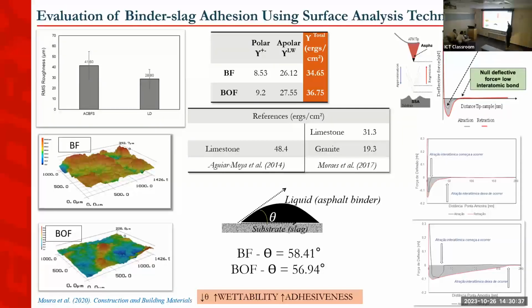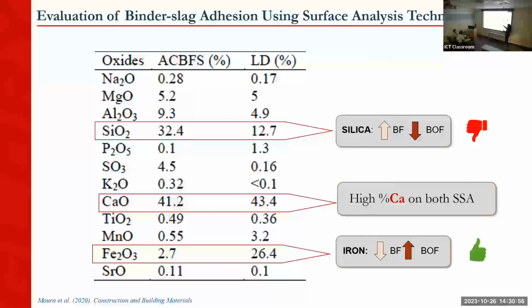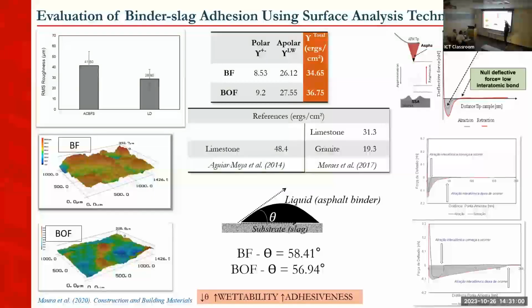Later, we took the AFM tip and dipped it into the asphalt binder. Then we approximated the tip to the slag substrate. From this test, we can measure how the atoms from the binder interact with the atoms from the slag. As the needle approaches the aggregate, they don't interact from a far distance, but as they get close, they start to influence each other until we have a good bonding between the atoms. Then when it comes back, they start to lose the force, the adhesion between them, until they no longer interact. The way to quantify this work of adhesion is to calculate the area of this graphic.